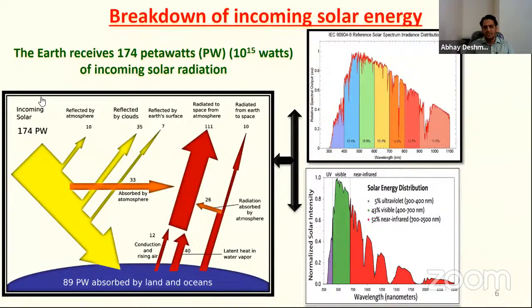And if you see the breakdown of the solar energy spectrum, 5% is ultraviolet energy, that is the 300 to 400 nanometer range, which is high energy. Then you have 43% visible light, that is 400 to 700 nanometer, and 52% near infrared energy, that is 700 to 2500 nanometer. So if you try to use the whole solar spectrum, obviously the amount of energy converted to a useful amount will be very huge.